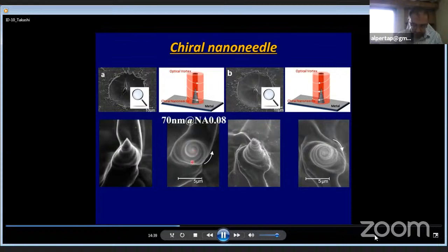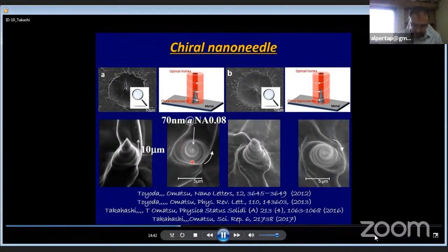The typical size of the needle is 70 nanometers in diameter. Absolutely sub-microscopic. The pulse spot size of the laser beam is about 30 to 40 micrometers, and the wavelength of the light source is typically 1 micron or 500 nanometers. We can achieve real nanoscale structured matter. That's quite interesting fabrication. This must be the magic microfabrication based on optical vortex.